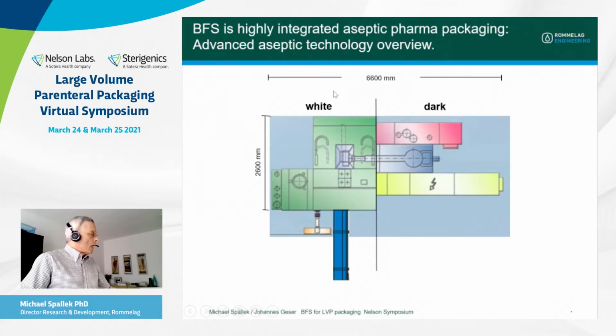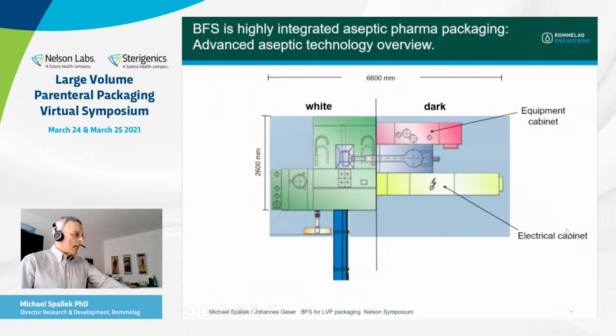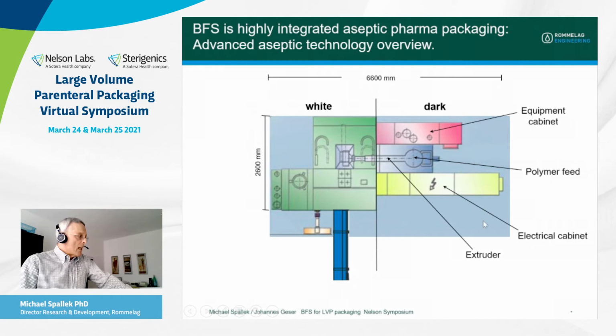Looking from above, this is a short layout of the system. So we typically have the separation into a dark side and a white side area. On the dark side, you have the equipment cabinet and the electrical cabinet. You have a polymer feed for the polymer granulate that feeds the extruder. The extruder melts and transports the molten polymer to the parison head, indicated here.